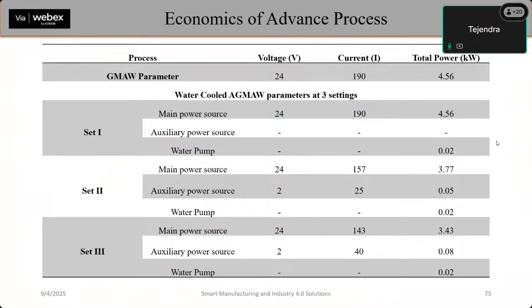However, for the advanced gas metal arc welding process that we have used for the WAAM process, three alternative parameter sets were applied. For set 1, the auxiliary power source was set to 0 voltage and current, replicating the normal GMAW method. In set 2, the voltage was set to 2 volts and the current was set to 25 amperes. And in set 3, a voltage of 2 volts and a current of 40 amperes were used.